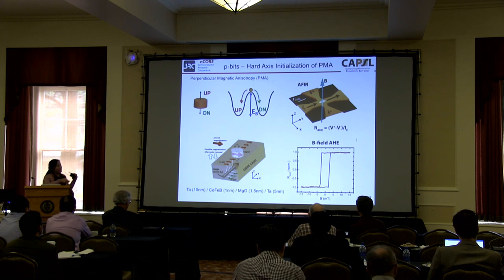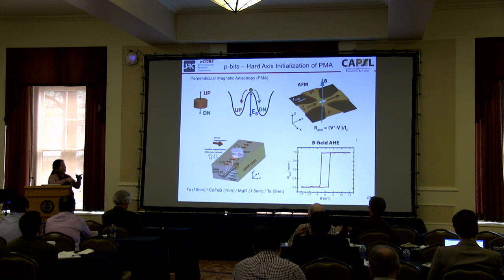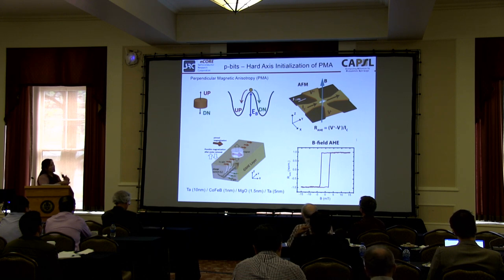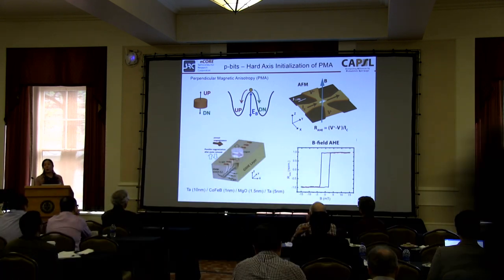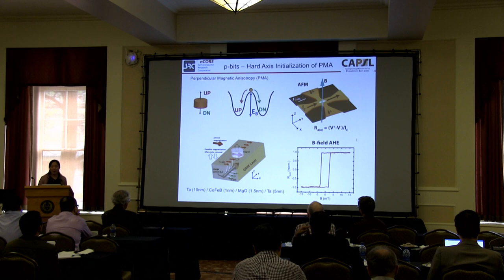But if we have an SOT effect from the giant spin Hall effect layer, once we pass the large SOT current, we will be able to pin the magnetization in-plane, into the hard axis. And once I let the SOT current go, because the easy axis is out-of-plane, it will either jump up or jump down with 50% chance again. So this is an electrical way of creating a stochastic magnet.